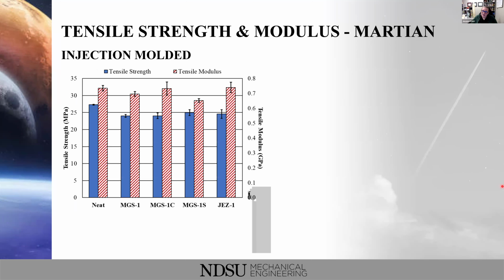So we look at some of our results. I compare both injection molding to additive manufacturing. That's the biggest thing that we're looking for within our materials. With our Martian composites here, again, we're looking at 40 weight percent loading within our polypropylene. We see very similar results to what we'd expect, right? We add 40 weight percent, and we're not seeing a whole lot of change within our tensile strength. Our tensile modulus also doesn't change a whole lot, which is something that we would expect with that rigid filler.